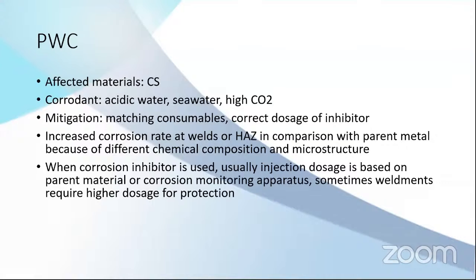And why is the mitigation the correct dosage of inhibitor? Because this also happens in a system where corrosion inhibitor is used. Normally, when we use corrosion inhibitor, we qualify how much inhibitor we need to add to the system to make it long lasting, to make the corrosion rate low. But this qualification we normally do with the parent material or corrosion monitoring like a coupon or corrosion probe, and we didn't do it on the weldments.